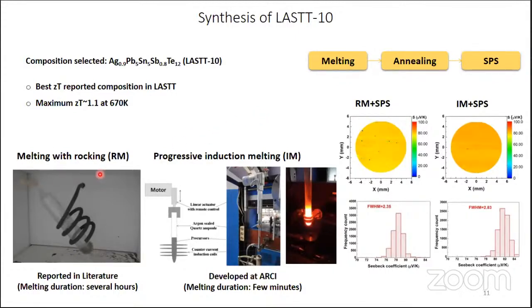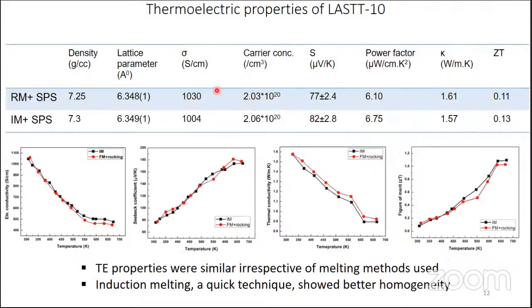And we made it by two methods. Both are melting routes, rocking as well as induction melting. This is a very slow process, and this is a very rapid technique. And what we got is, in both processes, since it's a melting process, only the melting methods are different. We are getting almost the same thermoelectric properties and densities. Everything is comparable. There is no significant change. So our properties are comparable with what is reported for this similar kind of material.